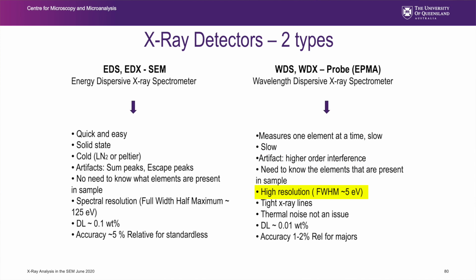They have much better resolution. Full width half maximum, crystal dependent here, but we're looking at about 5 eV. Very tight X-ray lines. So overlaps, that lead sulfur overlap that was a problem with EDS, is not a problem with WDS. Thermal noise is not an issue. Detection limits, routinely 0.01 weight%, and I can get better than that, okay? So that's 100 parts per million.